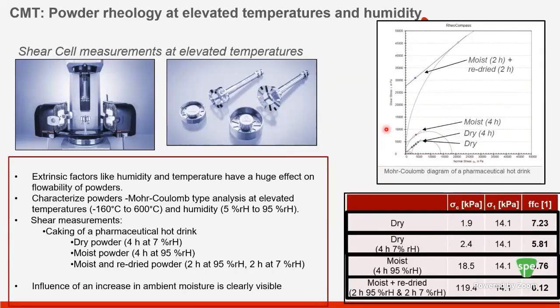Here especially I talked about ambient moisture, but we have done a lot of studies where we have studied temperature effects on polyamide powders which are used in additive manufacturing. So again, very unique experimentation is possible. And clearly these extrinsic factors actually have a huge impact on flowability, which drives a lot of the processing of these powders.